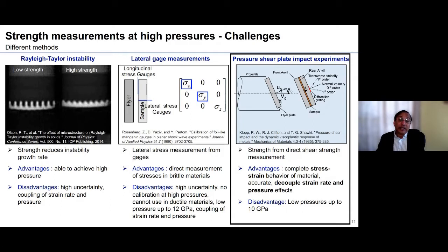And obviously, using something such as the Tresca condition, one can obtain the shear strength of the material by (sigma x minus sigma y) over 2. And this is a direct measurement of stresses, and it works extremely well in brittle materials. But once you have ductility, then there is high uncertainty, and also there is a limitation of the pressure at which you cannot measure the strength.